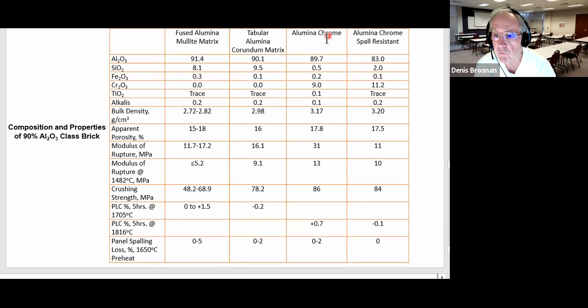Now, of course, there's the alumina chrome products. I spoke of these in an earlier lecture, some of the chemistries of those. Essentially, the spall resistant product has a much higher percentage of small pores in it than does the traditional product. Okay, so we have dual bands of pores in both products, coarse pores and fine pores, but a lot more fine pores in the spall resistant product.